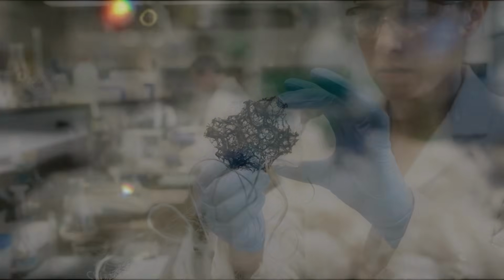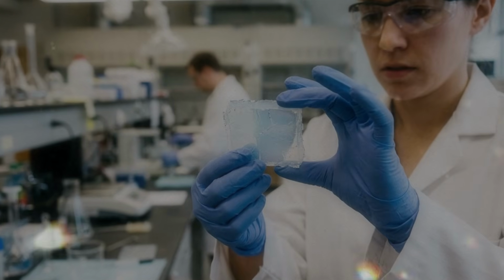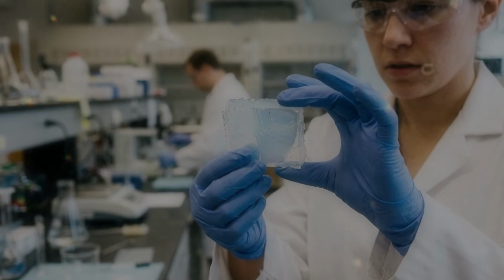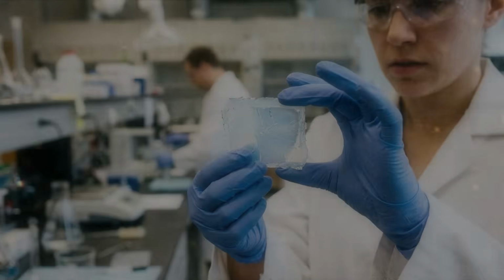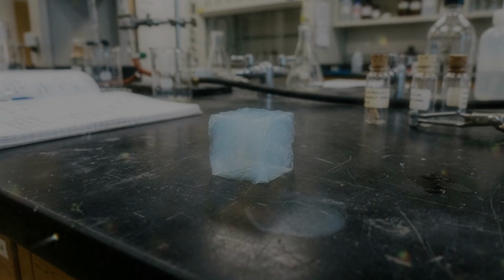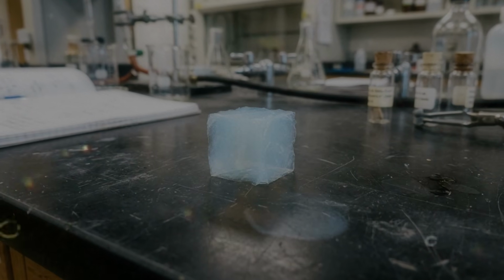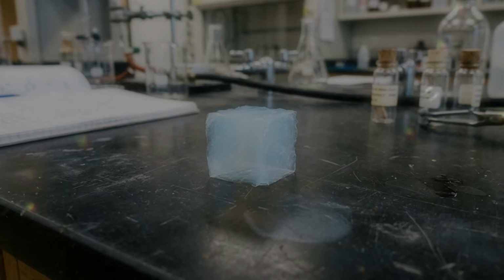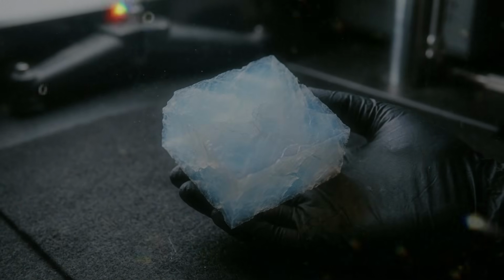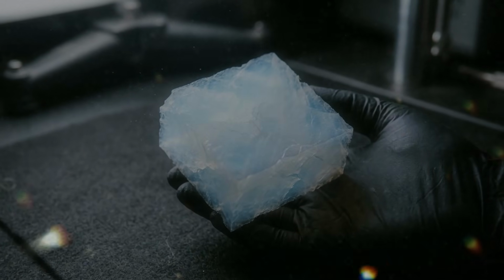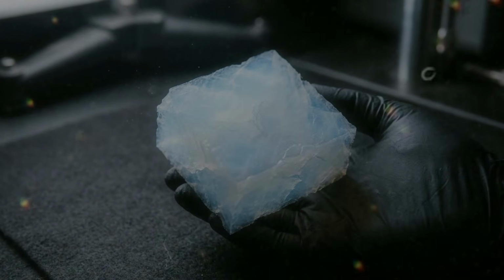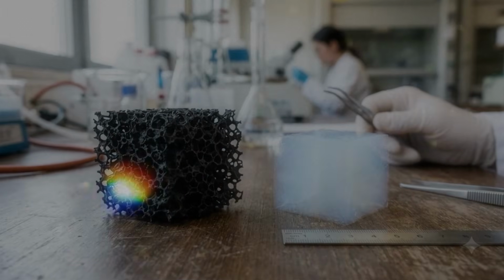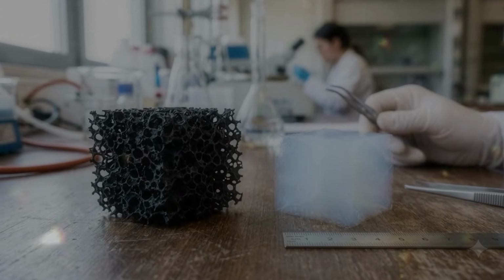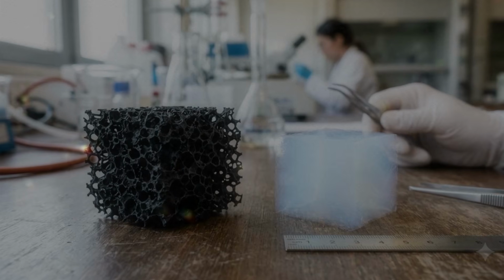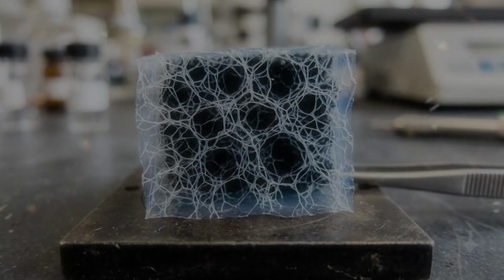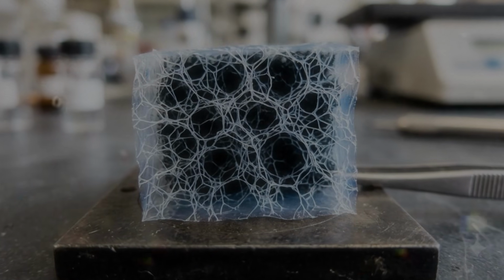It remains imperfect, and each improvement in one property may weaken another. Still, the combination explains why the material continues to attract attention long after its density record first appeared. It also explains why strength cannot be judged by appearance. The black sample looks like ash, or burnt sponge. Ash falls apart because its particles are poorly connected. Aerographene contains a continuous network. The amount of carbon is tiny, but it has not been scattered randomly.